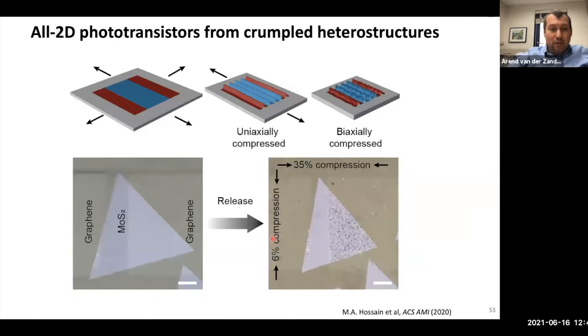So the way we do this, here's an example. We take graphene and we pattern the graphene into little squares, which we use as electrodes. And this triangle is CVD-grown molybdenum disulfide. So you see graphene, MoS2, graphene in this picture. Basically, the graphene is acting as an electrode and the MoS2 is acting as a semiconducting channel. If you know your electrical engineering, then what you'll see is that this structure is like a photodetector. It is a photodetector geometry.